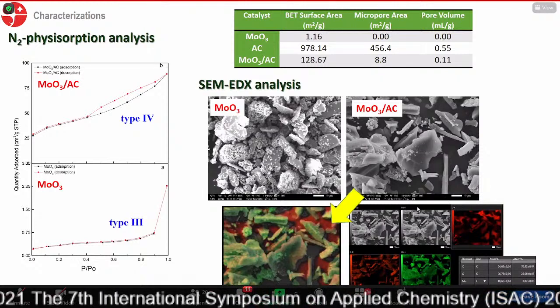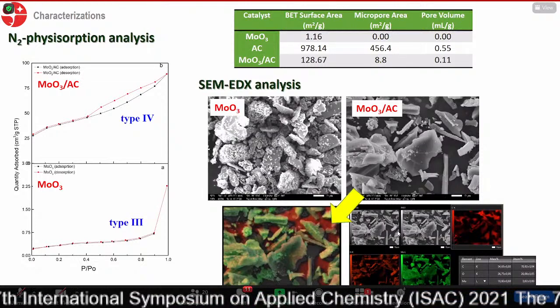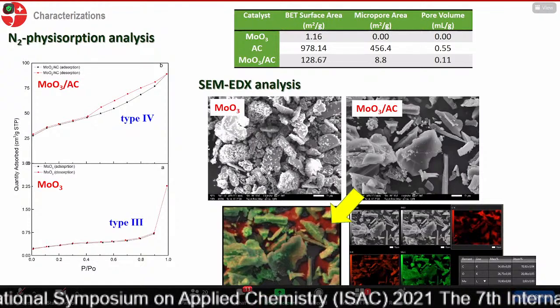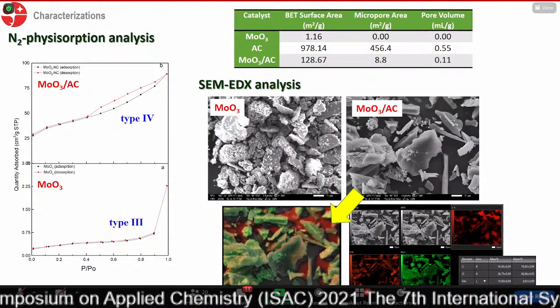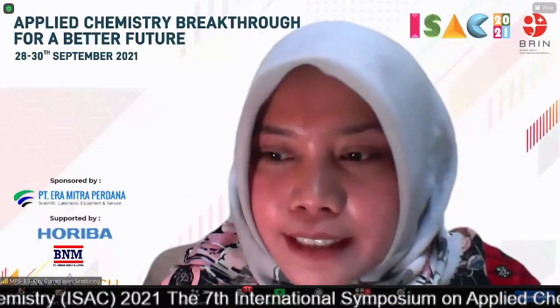So we cannot clearly see how big the molybdenum is on the surface of the carbon. And we believe that the dispersion of the molybdenum on the carbon is very good, since it covers all the parts of the carbon. So I think in SEM it is hard to clearly see the size of the molybdenum oxide. I see. Thank you for the explanation.